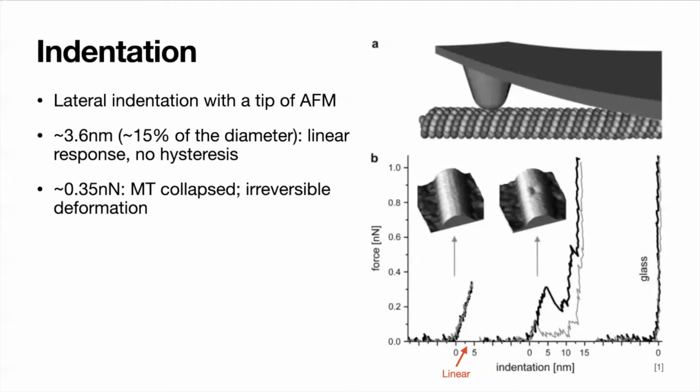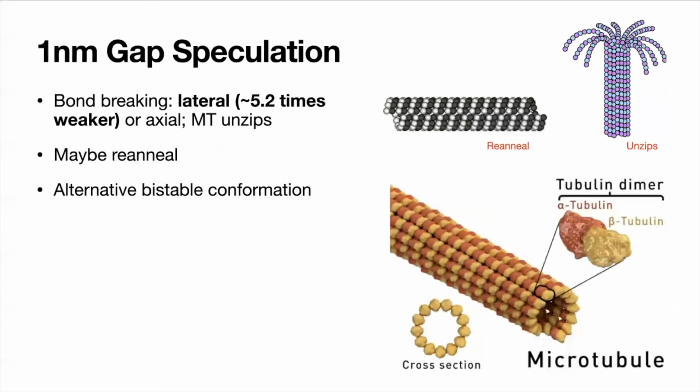If the force goes even higher, it may lead to substantial damage to microtubules. For example, depolymerization. The microtubules may fall apart. They may become long and thin protofilaments or even fall into small single particles. 0.35 nanonewtons may seem to be a small force for metals and crystals, but it is actually a pretty high value for such a small piece of biomaterial. Compared to other soft matter, microtubules take on a pretty impressive value of deformation. It is relatively strong.